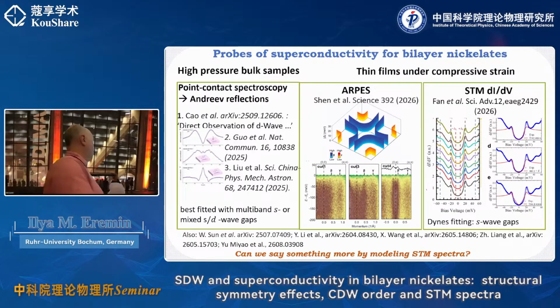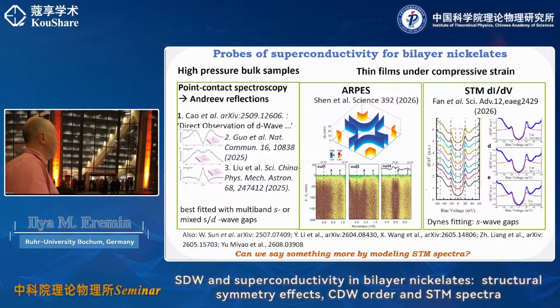In this case, essentially, you make an SN junction, and then you try to analyze the spectrum that appears, and you can also study the angle dependence depending on the rotation of the junction. Somehow the conclusions were not uniform. One of the groups claims that they did see a D-wave symmetry, a strong signature of D-wave symmetry, while the two other groups, which are from China, concluded it's also kind of anisotropic S-wave.